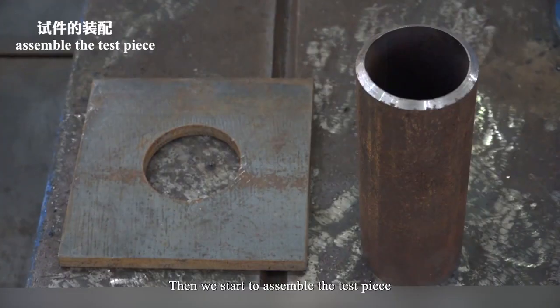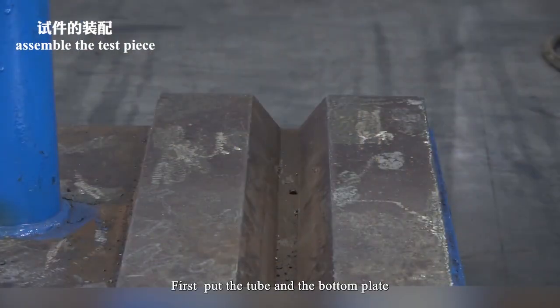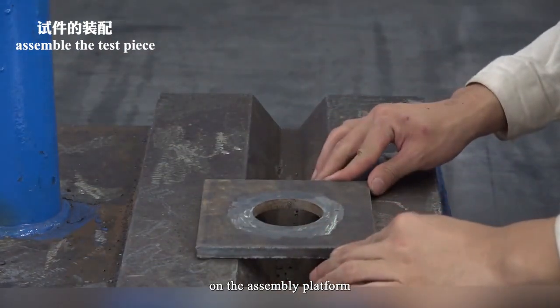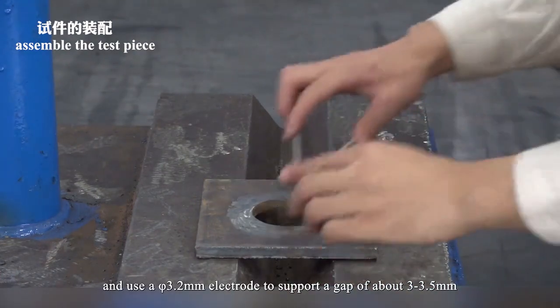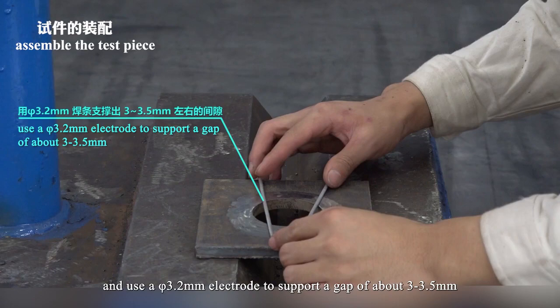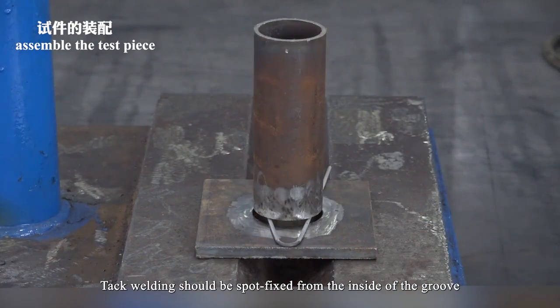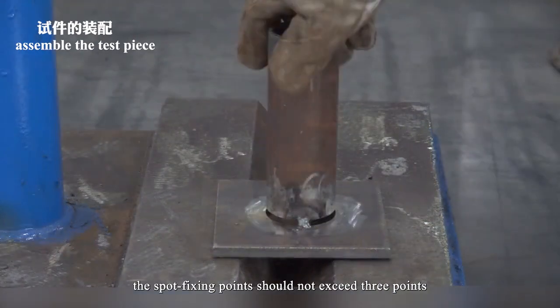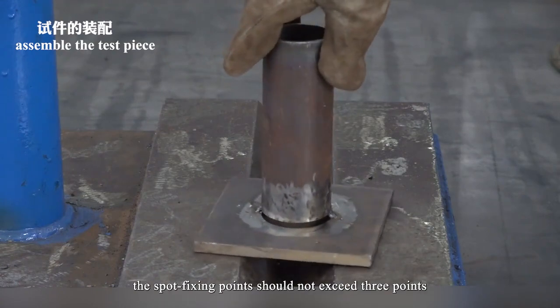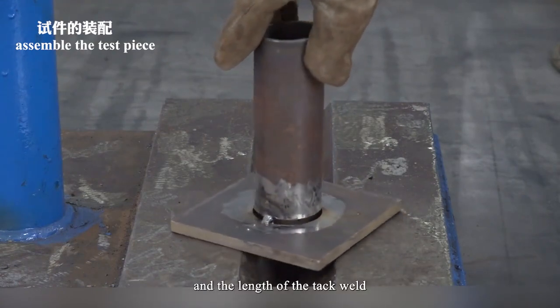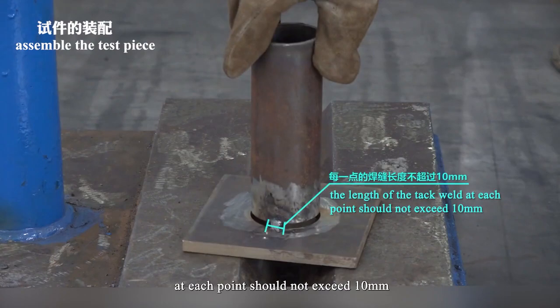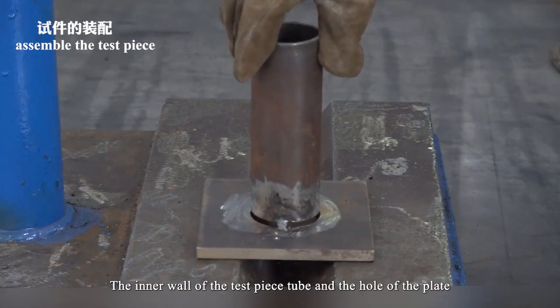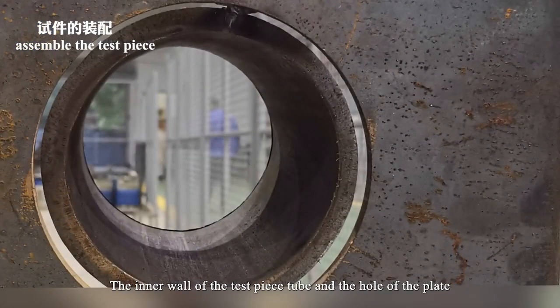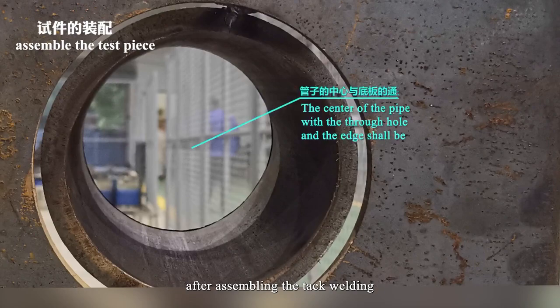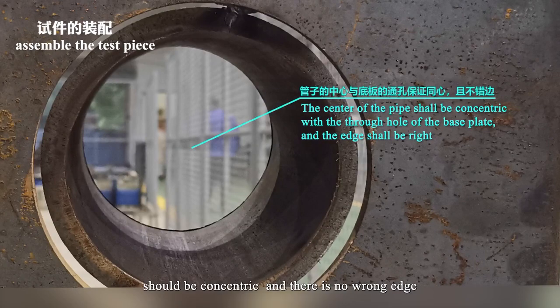Then we start to assemble the test piece. First, put the tube and the bottom plate on the assembly platform and use a 3.2 millimeters electrode to support a gap of about 3 to 3.5 millimeters. Tack welding should be spot fixed from the inside of the groove. The spot fixing points should not exceed 3 points, and the length of the tack weld at each point should not exceed 10 millimeters. The inner wall of the test piece tube and the hole of the plate after assembling the tack welding should be concentric, and there is no wrong edge.